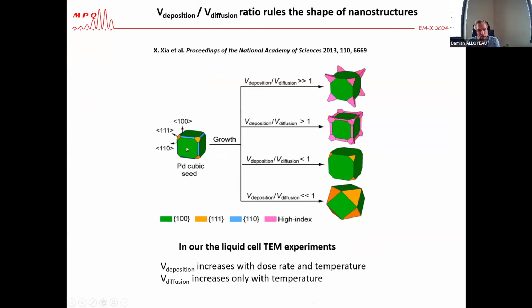where he has shown that starting from a cubic palladium seed, depending on the growth speed, if you are dominated by the growth speed, so by the deposition speed, you grow dendritic nanoparticles. If you are dominated by the diffusion at the surface of the nanoparticles, you form well-stable 1-1-1 facets. And in the intermediate regime, when you play with these two parameters, you are able to grow nanocubes.